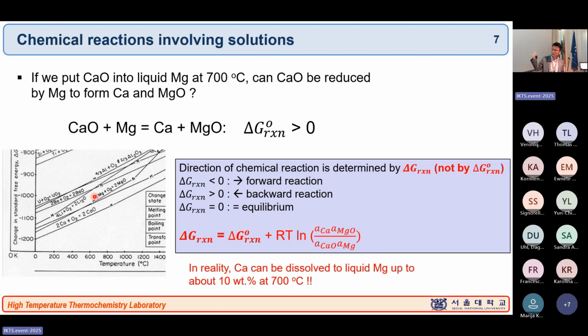Okay, this is actually about a $5 million patent in the magnesium industry, believe it or not. In the magnesium industry, people want to make pure magnesium alloys containing calcium. It has very good mechanical properties. But when you introduce metallic calcium, it always makes calcium oxide around it. So it always introduces the oxide, which deteriorates their mechanical properties. And this guy in Korea, accidentally, he put the calcium oxide on top of the liquid magnesium metal. And then he found out that calcium is going inside the magnesium metal and makes very high purity magnesium-calcium alloys without oxide inclusions.